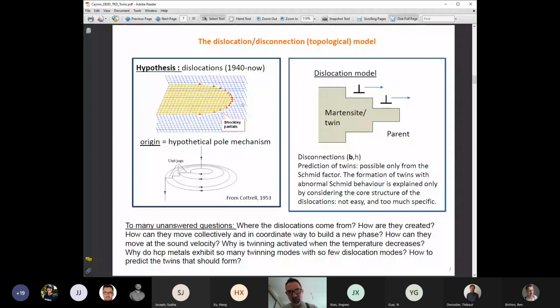There is also another theory, a little different from PTMC, that considers that it's impossible to do simple shear immediately. You know, it's famous in all textbooks, when you see an introduction to dislocations, it always starts by telling that it's impossible to apply a simple shear or to shear a plane directly, because if you look at the atoms, energetically the energy you need will be too much. So it will be easier to have a dislocation make a first small step, then another dislocation, and so on. So they imagine that for martensite or for deformation twinning, it was the same, that you need dislocations to produce the martensite or a twin.